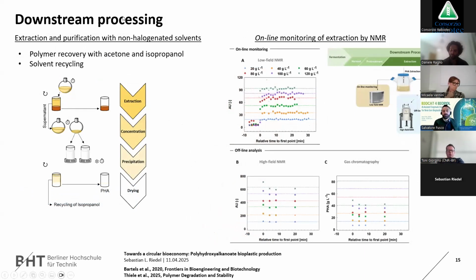For downstream, we have different approaches. We're focusing on green solvents, like acetone for the solvent and isopropanol for the precipitant. After extraction, you separate the cells from the solvent, and you can concentrate the solvent to reduce consumption. Then you precipitate it, wash it, and you get the PHA. Obviously this is more expensive than other options, but you get higher purities.